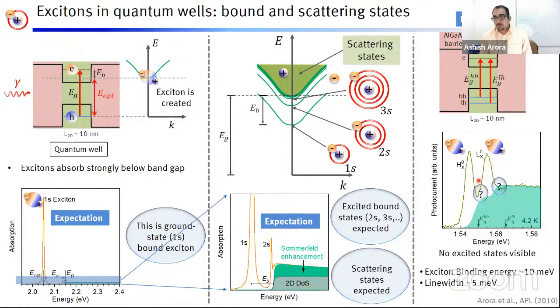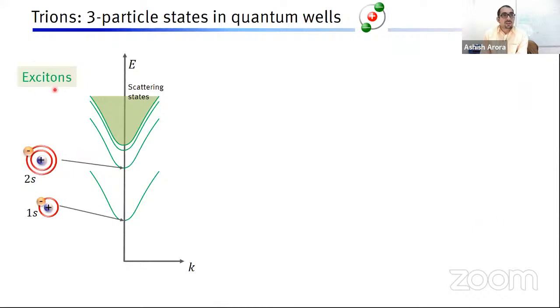However, we notice that there should be excited states of these excitons which are not visible here, because the binding energy is of the order of 10 meV, whereas the line width already is of the order of 5 meV. So the excited states of excitons here are merging. So it's very tough to see these excited states in quantum wells. You need very high quality samples in quantum wells. So with this message, let's go towards now trions.